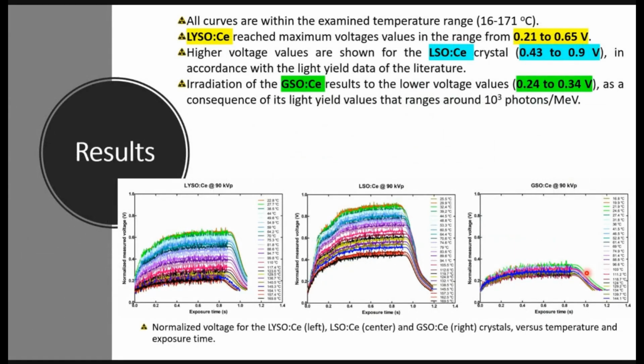Now we can pass to the results section. We can see three graphs showing the produced voltages with exposure time and temperature. The exposure time for all irradiations was set to 1 second, and as we can see from the graphs, after the 1 second, the signal stops. The crystal with the higher voltage values is the pure lutetium crystal, the lutetium oxyorthosilicate, and the produced voltages range from 0.43 to 0.9 volts.